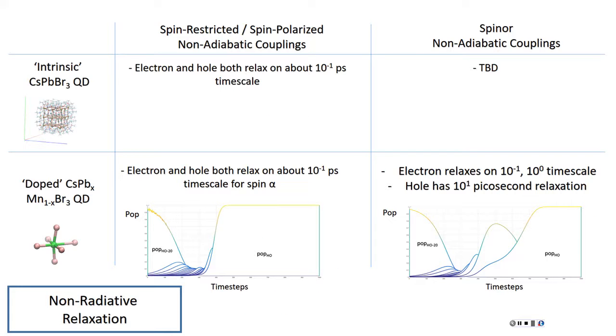I haven't fully completed these yet, because I'm working out some bugs with the code and the data. We just start with our intrinsic dot, comparing spin restricted and spin polarized non-radiative relaxation. They both relax to the band edges of the quantum dot at about 1 picosecond time scales. I'm not sure how that compares to the literature off the top of my head. I can't remember what the reported values are, I'll look at that. Spin-orbit non-adiabatic couplings for the intrinsic dot are work in progress. So it's a sub-picosecond range, right?